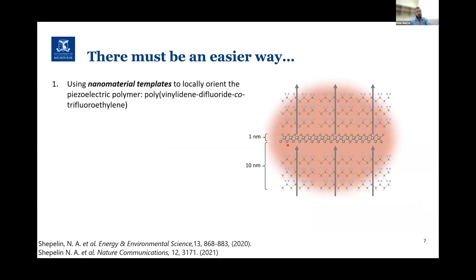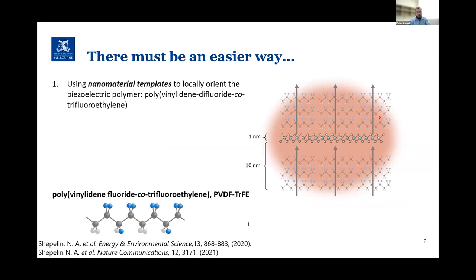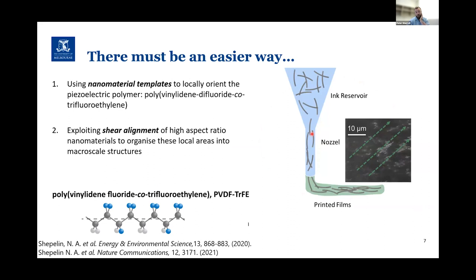But there simply has to be an easy way to do this. And what we've been looking at, as I hinted already, is trying to use a nanomaterial template and exploiting the properties of the nanomaterial to locally orient how those dipoles, how those crystallites align in a film. So the idea is to use something with a high aspect ratio, so all the polymer can adsorb onto the surface and stack in a certain way. Use a polymer with a really big dipole moment that addresses the assembly of the polymer into a crystallite. And then to align all these things, we go back to that aspect ratio point, which is we use 3D printing to attempt to get some sort of pseudo shear alignment of our nanomaterial in a polymer film, which then would lead to macroscale polarization.